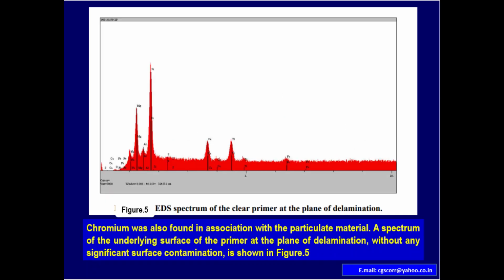Figure 5 shows the EDS spectrum of the clear primer at the plane of delamination. Chromium was also found in association with particulate material. A spectrum of the underlying surface of the primer at the plane of delamination without any significant surface contamination. You can see the peaks of magnesium, aluminum, silicon, sulfur, chromium, titanium, and so forth.